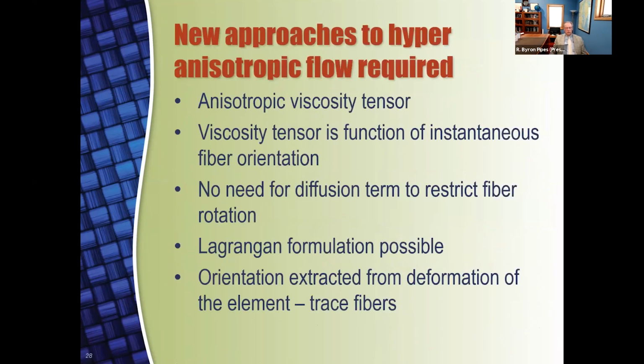So what happened was that we needed, and we provided, a new approach, something with an anisotropic viscosity tensor, where the viscosity itself was a function of the instantaneous fiber orientation, where there was no need for this diffusion term to restrict fiber rotation, where Lagrangian formulation was possible, and we could extract the orientation from the deformation of the element and trace fibers.